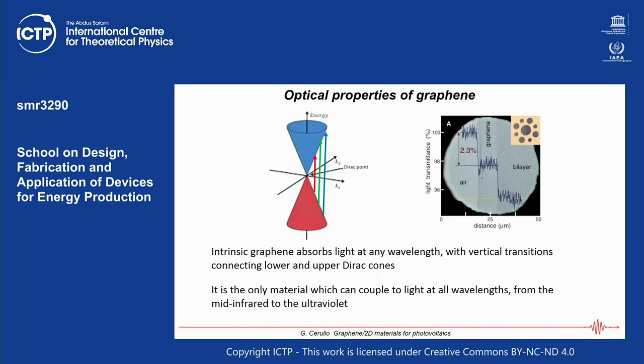This peculiar electronic structure has important consequences for optical properties. An optical transition is typically vertical — connecting states with the same wave vector — since a photon has negligible momentum. In intrinsic graphene, with electrons in the valence band and an empty conduction band, you can make these vertical transitions at any photon energy, at any frequency. Unlike a semiconductor with a band gap, where you cannot absorb below the gap, graphene can absorb light at any wavelength — from mid-infrared to the ultraviolet.